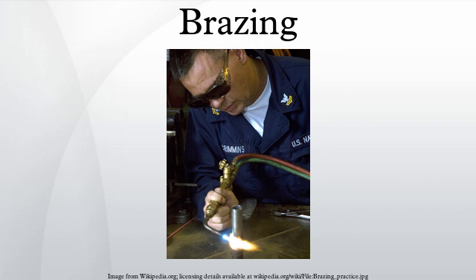Embrittled with sulfur and some lower melting point metals, for example zinc. Boron, phosphorus, silicon and carbon lower the melting point and rapidly diffuse to base metals. This allows diffusion brazing and allows the joint to be used above the brazing temperature. Borides and phosphides form brittle phases. Amorphous preforms can be made by rapid solidification.